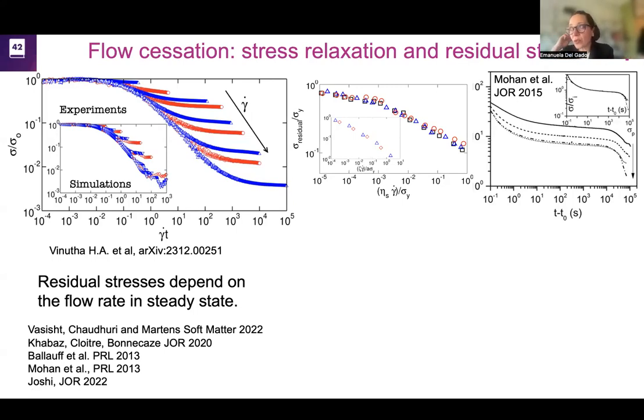And this is not due to the inertia of the rheometer. It's in a condition in which we have been able to exclude all those effects. So it's really the relaxation dynamic of the system that is doing something that in fact depends on the rate at which the system was flowing. And the stresses relax down to a value that in fact is non-zero. So they don't relax completely, so that people refer to them as residual stresses. But even the value of the residual stresses depends on the rate.